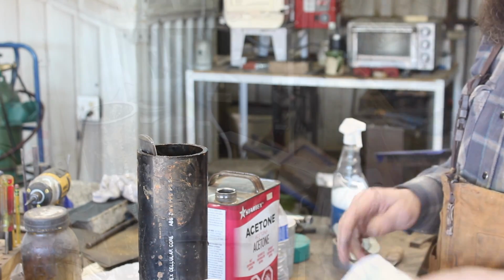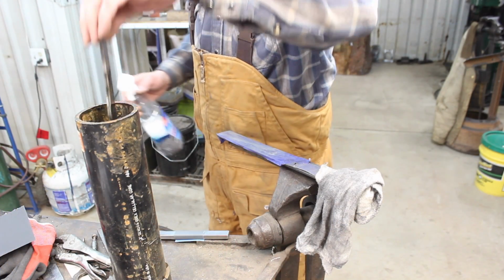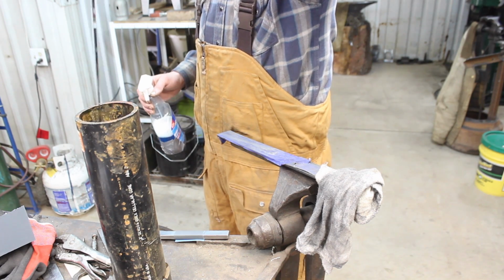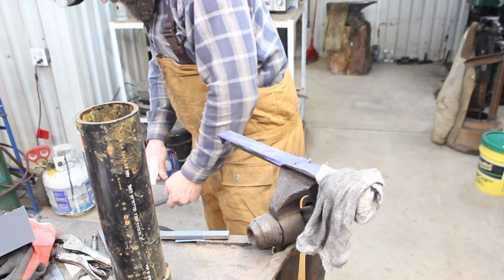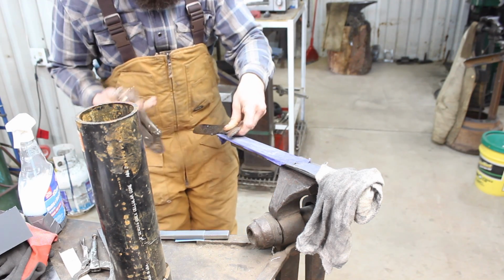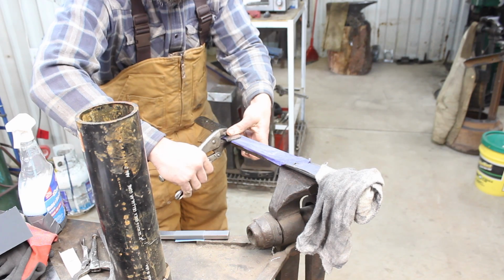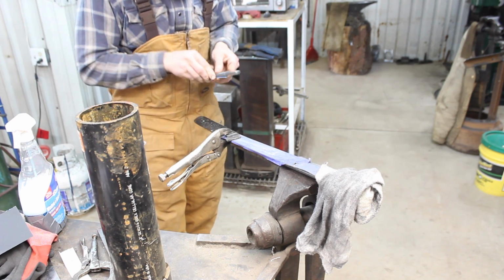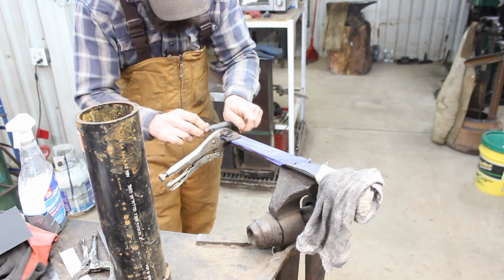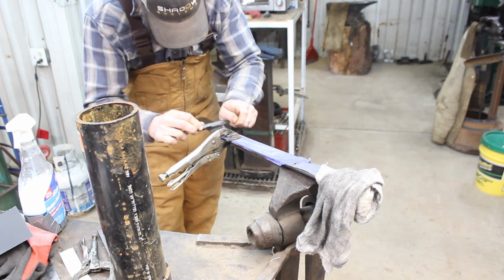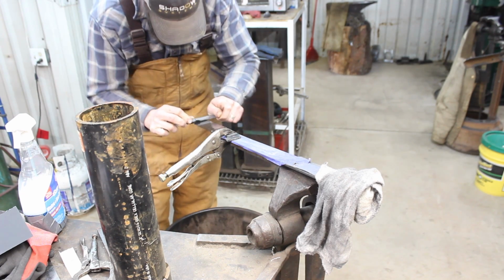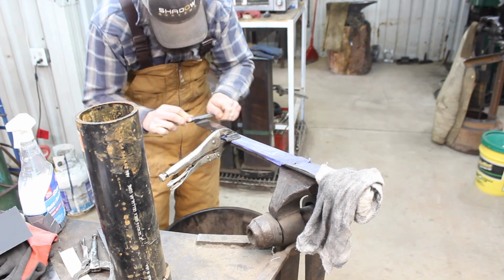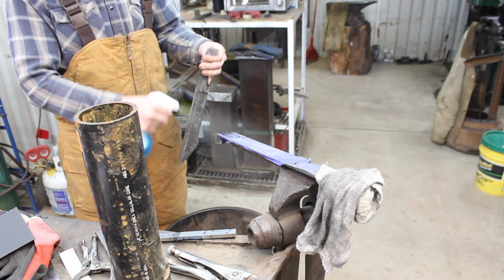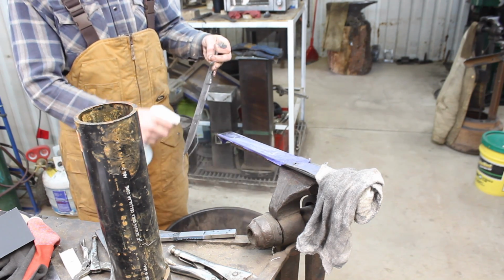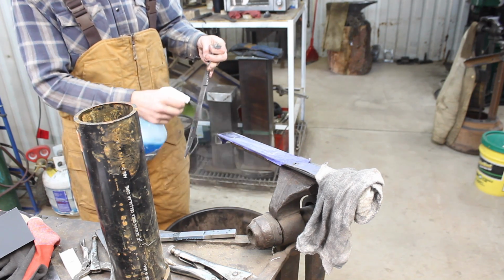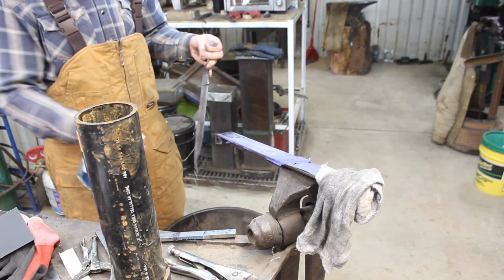You'll notice that it's a fairly weak solution of ferric chloride. That PVC or black pipe tube is almost full of water, up to within 4 inches of the top, I believe, and I probably raised the level about 2 inches with the ferric chloride. So not a super heavy concentration, and that's what you want. You don't want your ferric chloride so strong as to attack the nickel content steel to the same degree as the carbon steel. If this happens, it will be very difficult to achieve a deep, crisp, and high contrast etch on your blade.